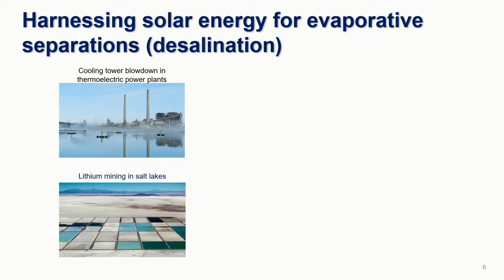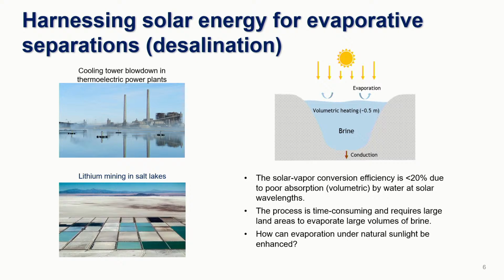Now the challenge with just doing this very passive solar evaporation is that when sunlight comes in, it is absorbed by a very large volume of water. So water volumetrically absorbs sunlight because it's fairly transparent in the visible and the near infrared range. So as a result, your conversion from sunlight to vapor is pretty low. It's only about 20% conversion.